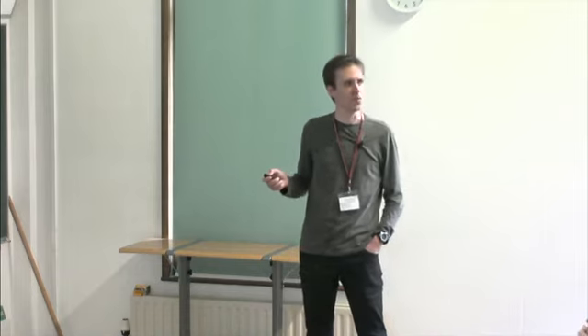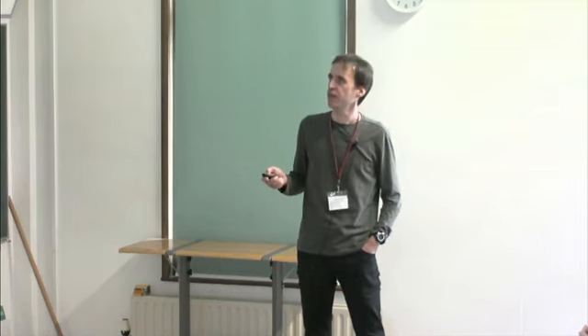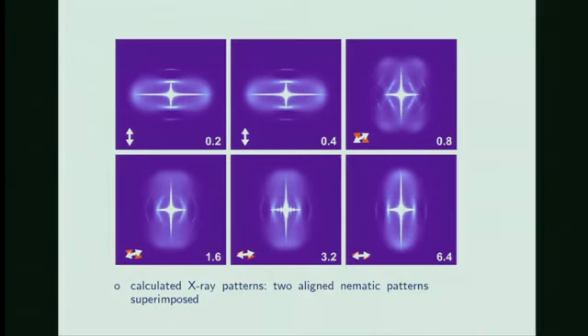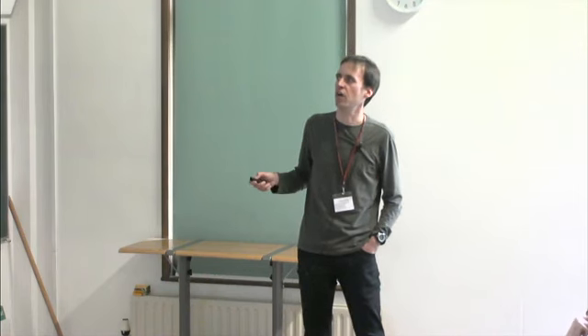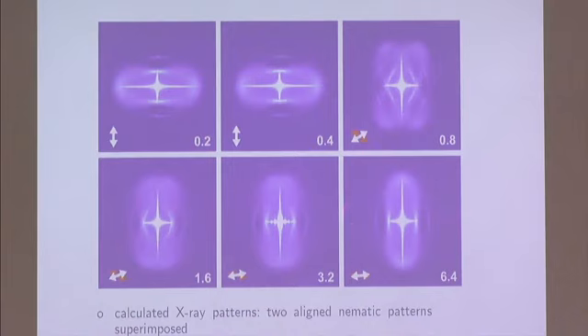This was also then observed in the Urayama experiments, and of course, one can also expose the sample to X-rays. Initially the director is pointing along the Z direction, and so we have the familiar nematic pattern. Again, please ignore this central cross here. And then above the threshold, we have superimposed signatures from the two domains. So there are the two corresponding directors here. And going to a very strong field, an almost 90-degree rotation is accomplished for the director.